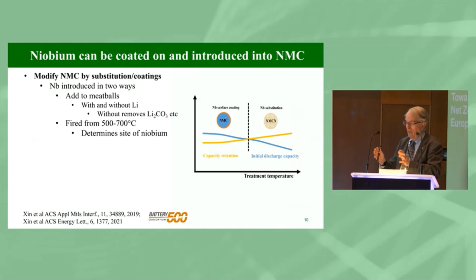We've introduced the niobium in two ways, initially taking our meatballs and soaking them in a niobium solution and firing them up at a temperature. And depending on the treatment temperature, at low treatment temperatures, we get a surface coating. At high temperatures, the niobium goes totally within the lattice. And what we found out, surface coating gives us better capacity retention, but the bulk coating gives us a higher initial discharge capacity.